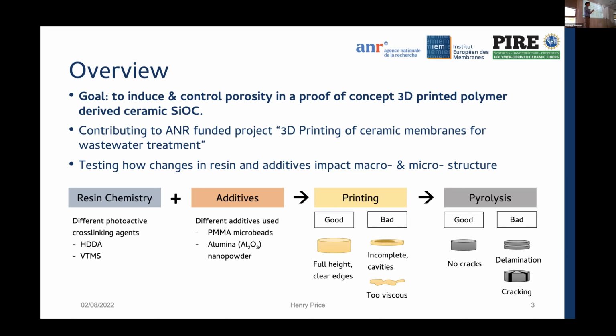So just to give you a quick overview of some of the things that could cause a failed test: after printing, sometimes the print would not fully complete, and sometimes if the resin was too viscous, it could not print at all. I'll get into this more specifically later, but this is affected by the chemistry of the resin as well as the additives.